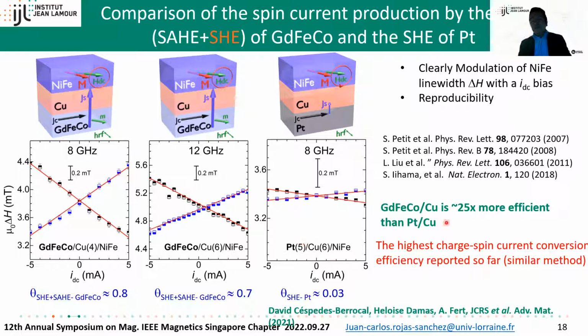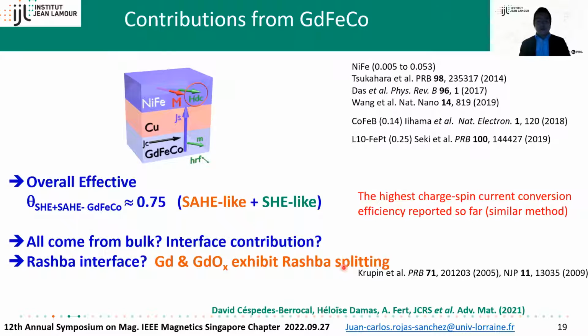So that is nice. We expected a large effect here, but it's really large in the GdFeCo interface with copper, 25 times more efficient than platinum copper. So that is one of our main results in this work. We have overall 25 times the efficiency in GdFeCo copper compared with platinum. But still, we have some open questions.